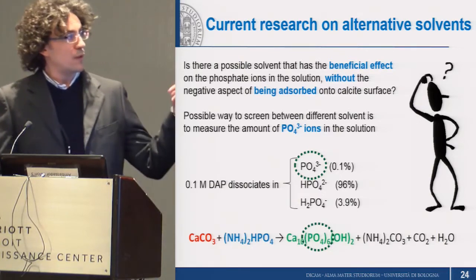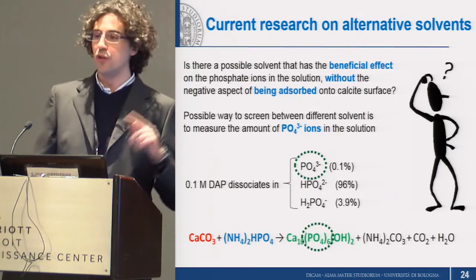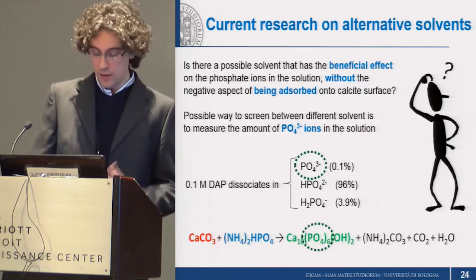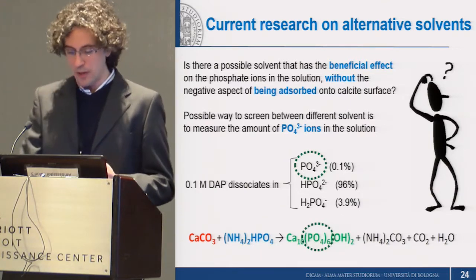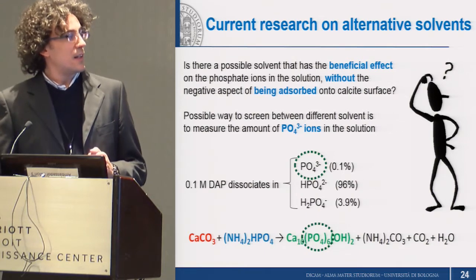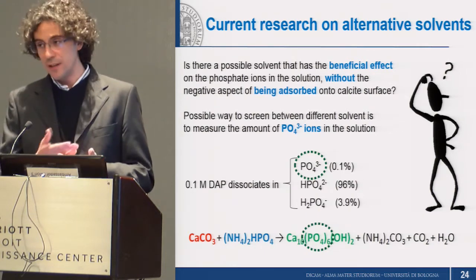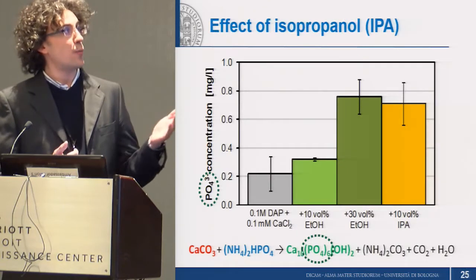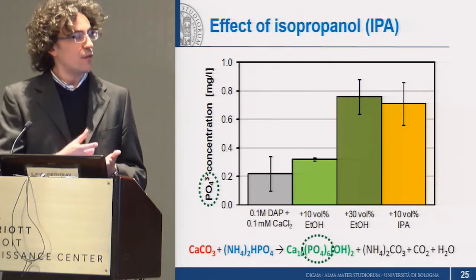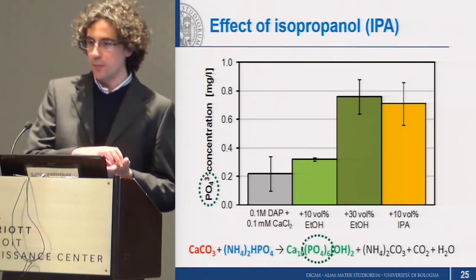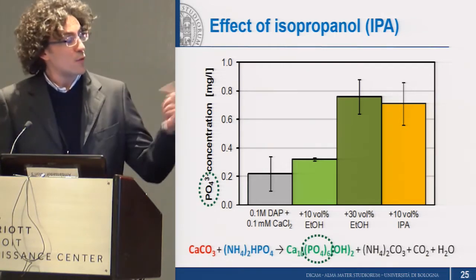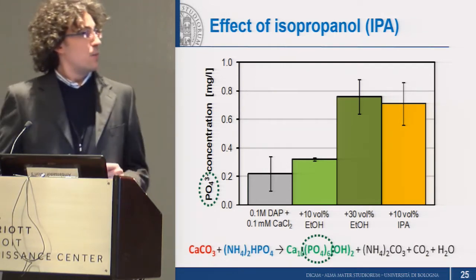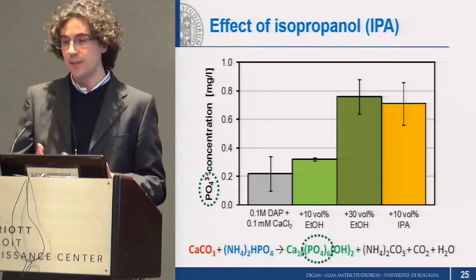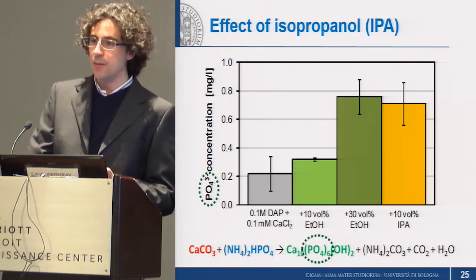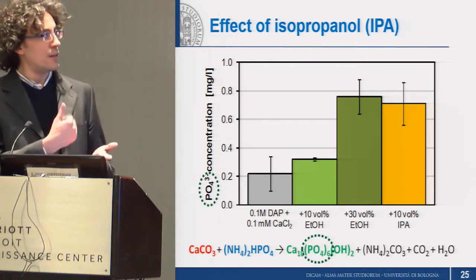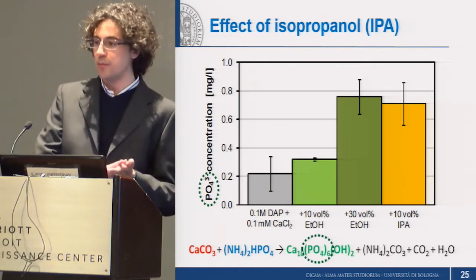To do so, we thought that measuring the concentration of phosphate ions in the solution could be a good and relatively rapid way. So the first thing that we thought about was using isopropanol, IPA, because of the bigger molecules, as a possible substitute for ethanol. And what we found was that in terms of PO4 concentrations, an addition of 10% IPA basically gives us the same amount of phosphate ions as 30% ethanol.